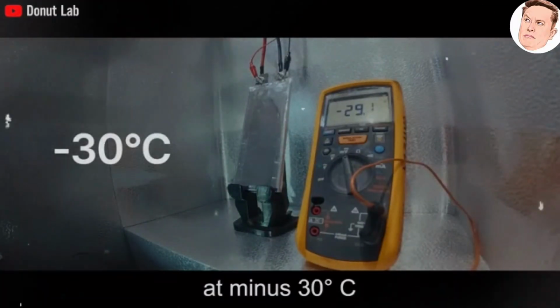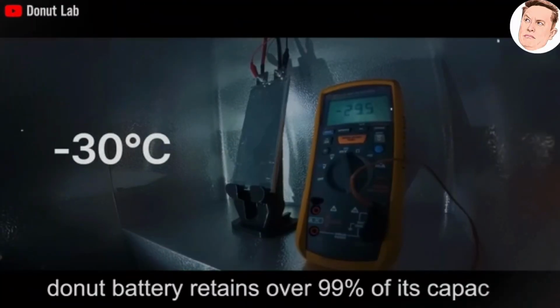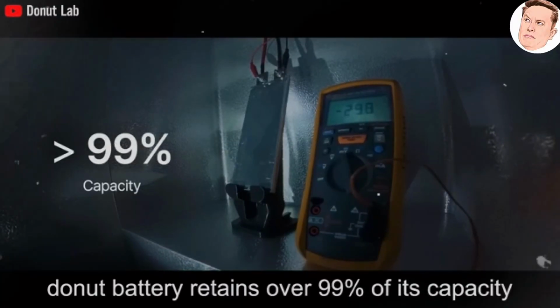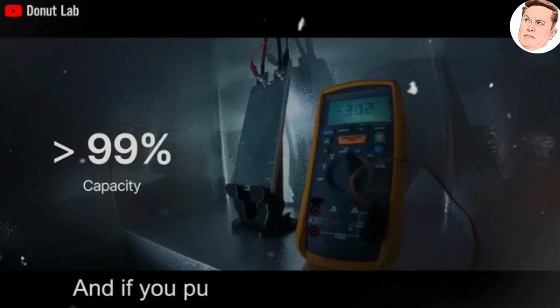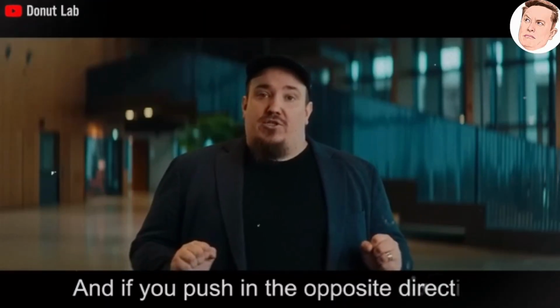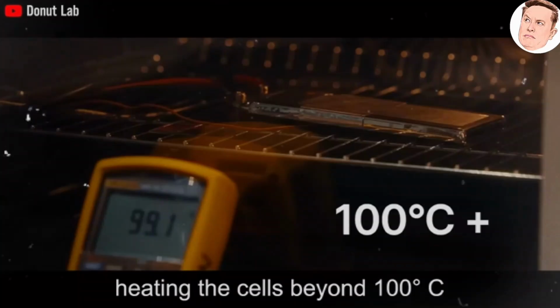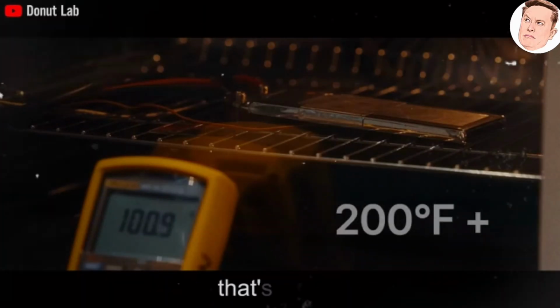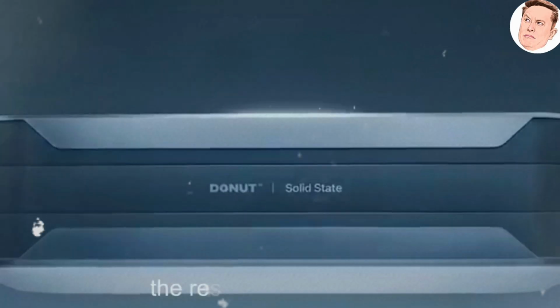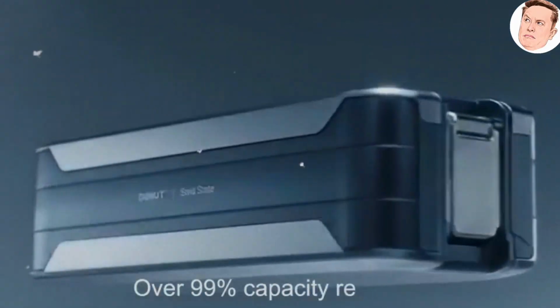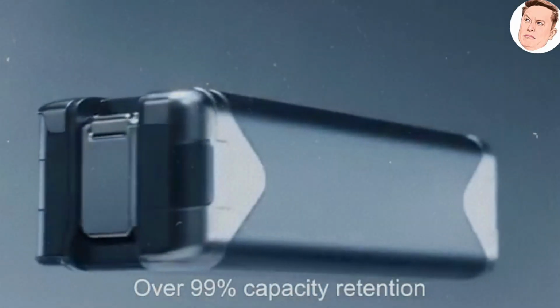At minus 30 degrees Celsius, the Donut battery retains over 99% of its capacity. And if you push in the opposite direction, heating the cells beyond 100 degrees Celsius, that's 212 Fahrenheit, the result stays the same: over 99% capacity retention.